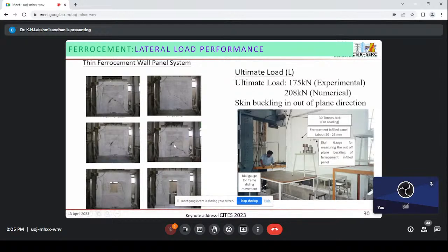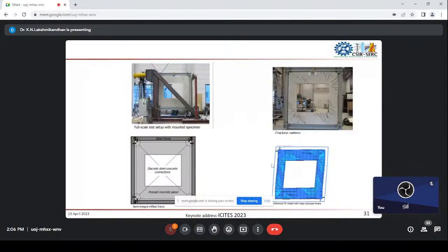That is the out of plane direction. In the out of plane direction, the cracks form, and the bricks move out of plane and fall down, as they do not have enough capability to hold together. But in ferrocement, the case is different, it has enough strength to hold together. As a result, the entire system acts together till the ultimate failure, and it avoids the falling of any concrete. This way, ferrocement is a very high demand composite for the construction industry.